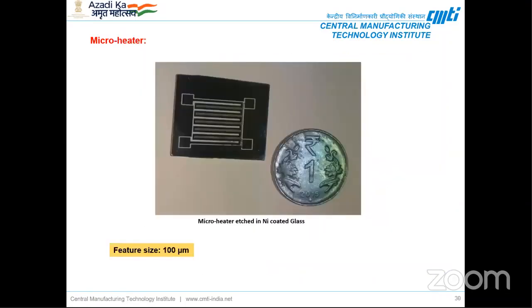Another application is a micro heater. Here, this is a glass coated with nickel of a few nanometers. We have etched this nickel coating without affecting the base substrate. That means based on the design of the micro heater, we have etched out the nickel coating from the glass. The minimum feature size here is around 100 micrometer.